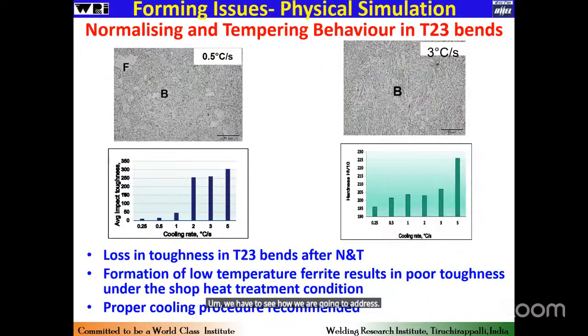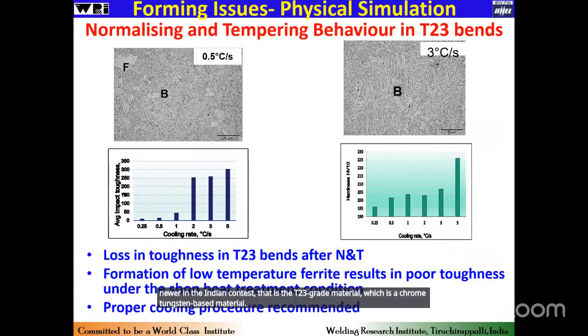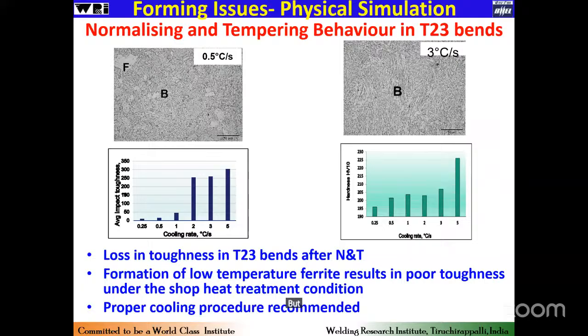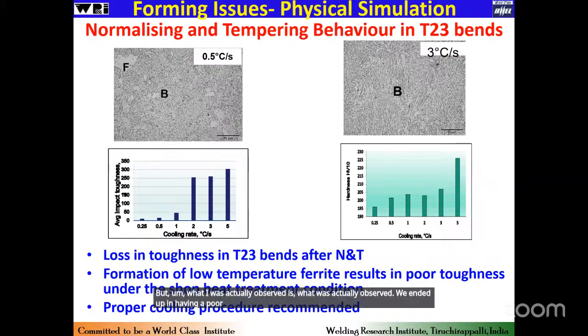And this is one of the not very new materials, but of course it is newer in the Indian context. That is a T23 grade material, which is a chrome tungsten based material. What we have observed is that after the bend forming, a typical normalizing and tempering heat treatment is carried out. But we ended up having a poor toughness after we do these normalizing and tempering treatments.